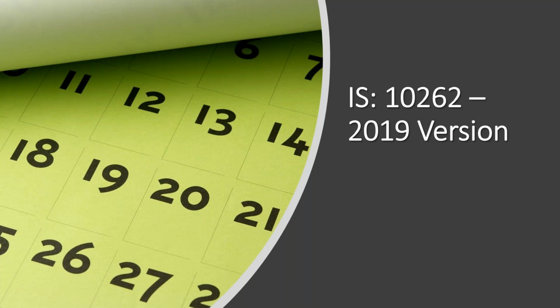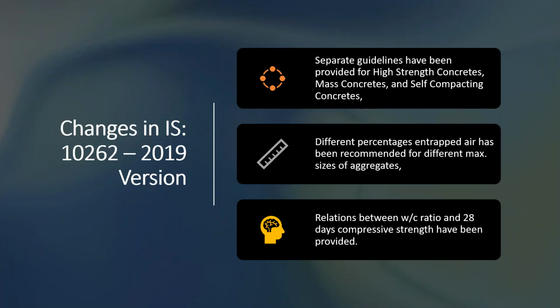Then what are the changes in the 2019 version? Because after that, IS 10262 was further revised in 2019. Changes in IS 10262 2019 version: separate guidelines have been provided for high strength concrete, mass concrete, and self-compacting concrete in this code. Earlier, these guidelines were not there. Different percentages of entrapped air have been recommended for different sizes. Earlier, entrapped air was removed; now it has been reintroduced. And relations between water cement ratio and 28 days compressive strength have been provided. Earlier it was removed, now it has been introduced.